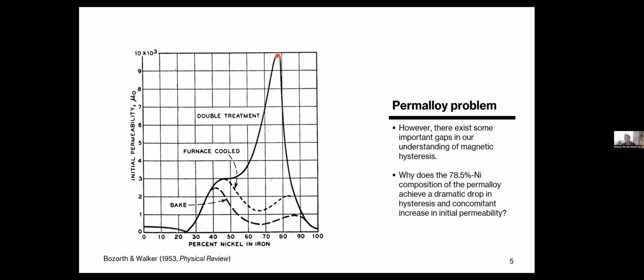The question they asked was, why exactly is this composition giving you the smallest hysteresis? So for each of the specimens they made, they went and measured the fundamental material constants. And what they found is kind of surprising, and I'll tell you why. The softest magnet, at 78.5% nickel content, has an anisotropy constant that is actually not zero. The anisotropy constant, in fact, goes to zero at a composition of 75%, but that is not the magnetic alloy that shows the largest permeability or the smallest hysteresis. Another interesting feature was a second peak in this curve, at 45% nickel in iron, which is also one of the soft magnets. But in fact, the anisotropy constant of this composition is very large.